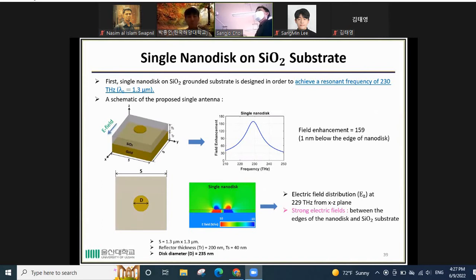We start from the single nanodisk on silicon dioxide substrate. Our single nanodisk is optimized to achieve a resonant frequency at 230 terahertz or 1.3 micrometer. And this is the schematic of the proposed single antenna. So we use also the substrate size of 1.3, which is 1 lambda. And also we set the reflector thickness to 200 nanometer and the substrate thickness to 40 nanometer. And also with this diameter of 235 nanometer.